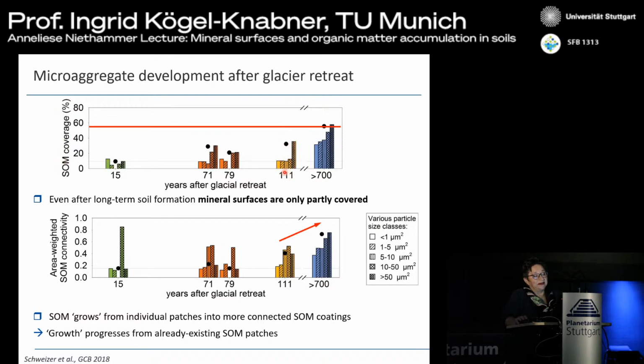Specifically in the very fine materials that are still finely associated organomineral associations, and also in the mature soil. But what we also see is that even after a long time of soil formation, these mineral surfaces are only partly covered. In this case, I think it's something like 59% or so at the maximum. And we also see, if we look at the connectivity of the organic matter, that this increases with time, specifically in the mature soil.